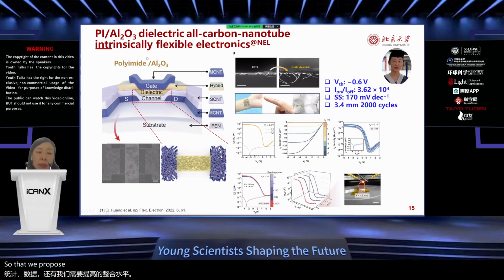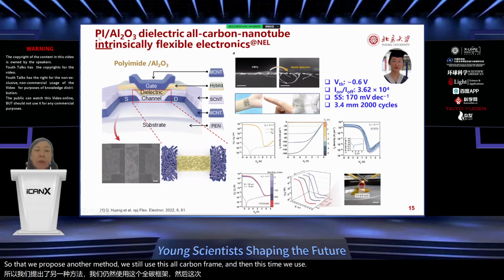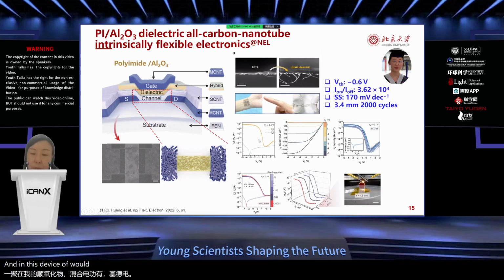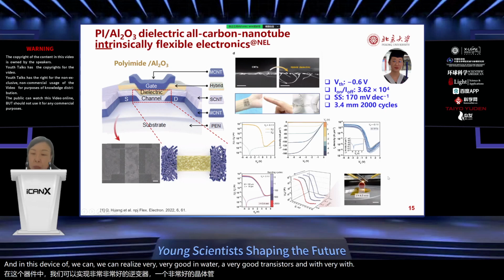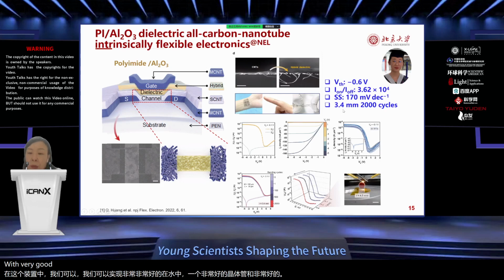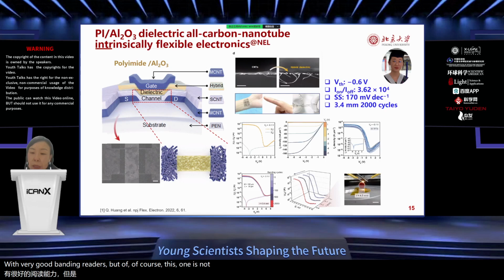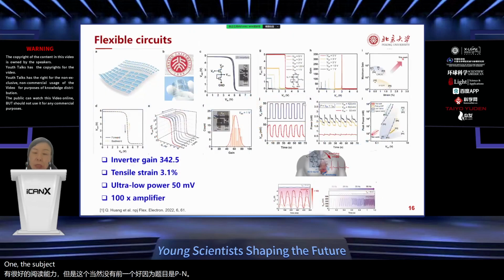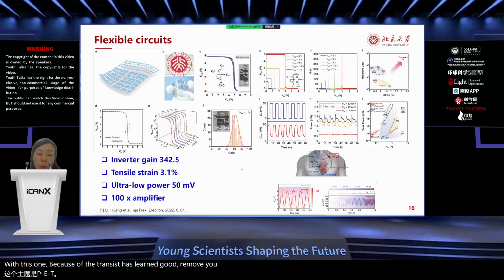So we propose another method. We still use this all-carbon frame, and this time we use a polyimide and aluminum oxide hybrid dielectric to work as the gate dielectric. In this device, we can realize very good inverters, very good transistors, and with fairly good bending radius. But of course, this one is not as good as the previous one because the substrate is PEN. The previous one, the substrate is PET. But with this one, because the transistors have very good uniformity and narrow variation, the circuit works very well.